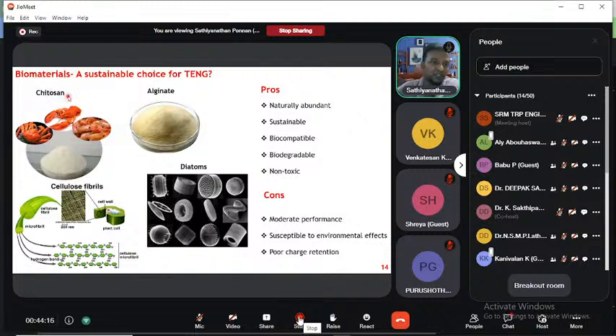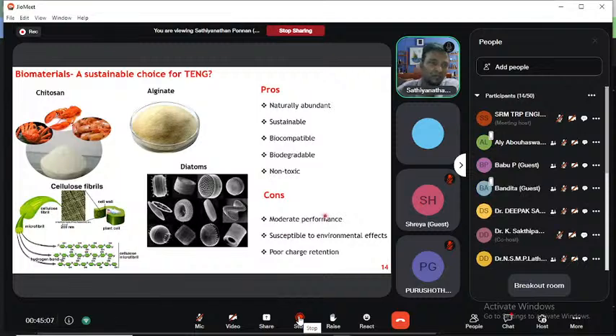I chose chitosan because, compared with alginate, diatoms, and cellulose fibrils, chitosan shows good performance and the processability is quite easy. So I chose chitosan in this case. What is the disadvantage of using biomaterials? Till now they show very moderate performance, and retaining surface charges is quite difficult, because biomaterials can easily absorb moisture from the water. They easily absorb water molecules, and that neutralizes the charges. So poor charge retention and moderate performance are the biggest issues of using biomaterials in TENG systems.